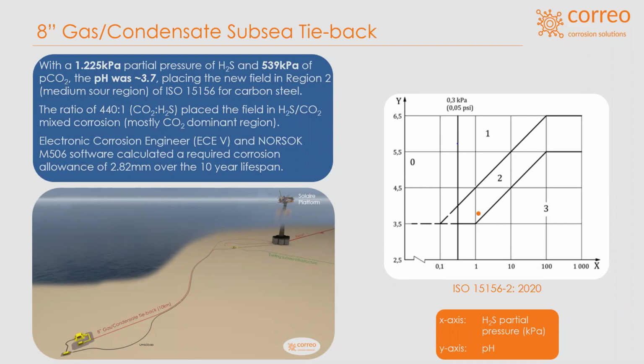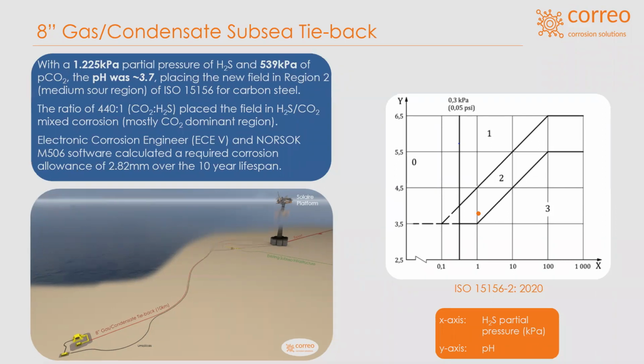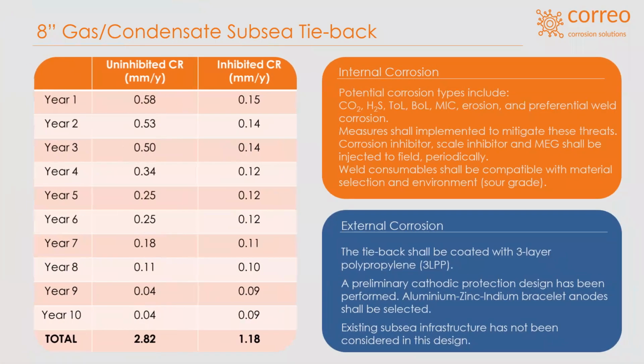So we took this into account when we used electronic corrosion engineer software corroborated by NORSOK M506 to calculate our corrosion allowance to be 2.82 over our 10-year lifespan. So we can see that in the table here to your left. We can see that our corrosion rates between year 1 and year 3 are higher than the rest. This is because we don't have any water running through, so no bicarbonates, which meant that this wasn't a buffer, so it was a slightly higher pH. So our pH does lower in years 4 onwards.